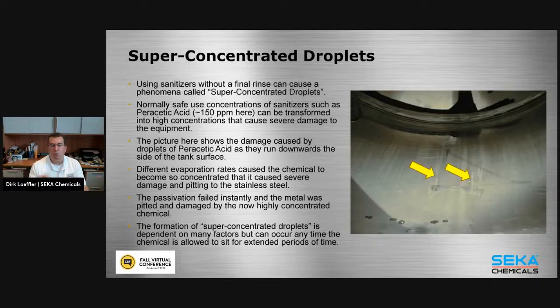So again, if we don't rinse our chemical, in this case peracetic acid, we started with 150 parts per million. It was at the top of a tank. The tank hadn't been used in a while, and the PAA was just sitting there. Well, the problem is PAA is not just PAA. You're looking at several different chemicals that coexist in an equilibrium, and they evaporate at different ratios. Unfortunately, it seemed in this case the water evaporated first, leaving us with a very, very highly concentrated peracetic acid solution. And at those high concentrations, peracetic acid does become corrosive on stainless steel.